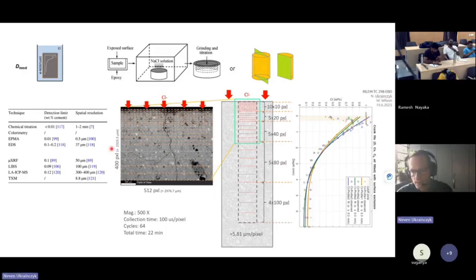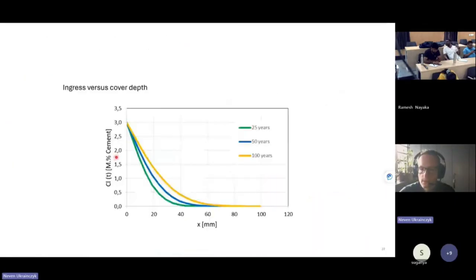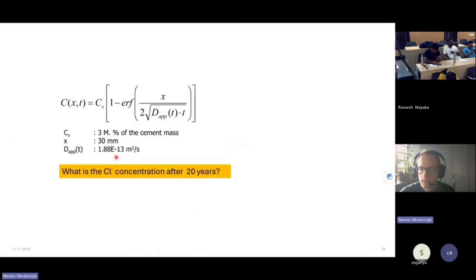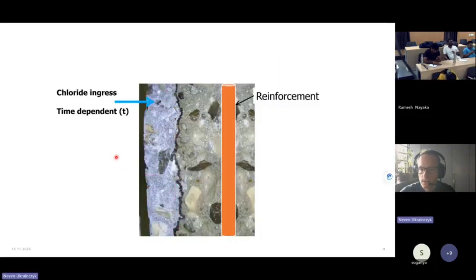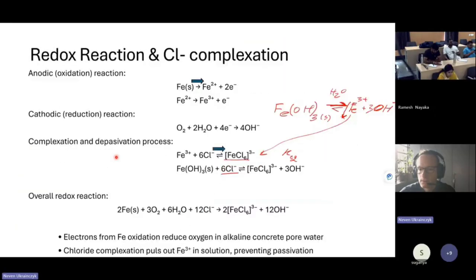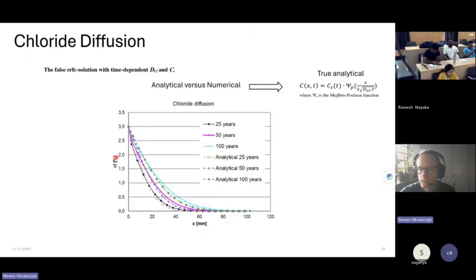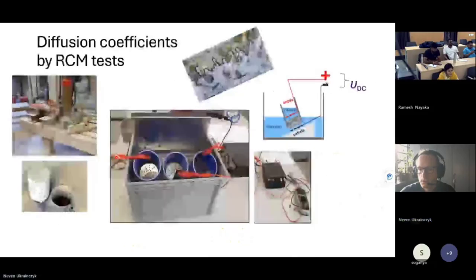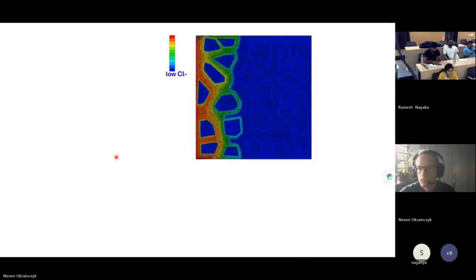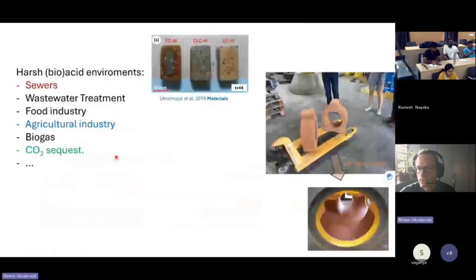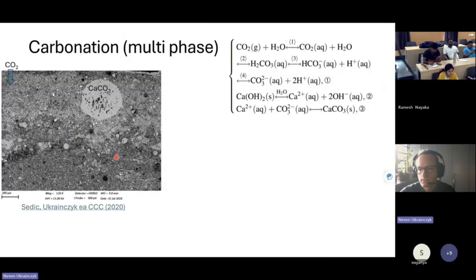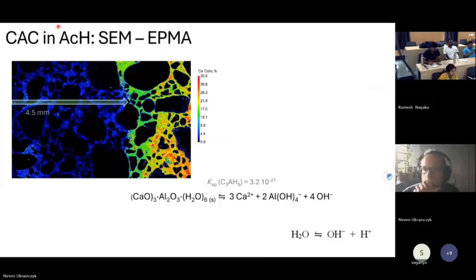Maybe if you would use EPMA, this is what we did here, but this was really high resolution. This is a very advanced technique. They did it in Graz. Oh no, it was later. It's a field gun, so you really need a good field emission. This is field emission, very strong intensity electron beam, a field emission SEM with electron probe microanalysis.